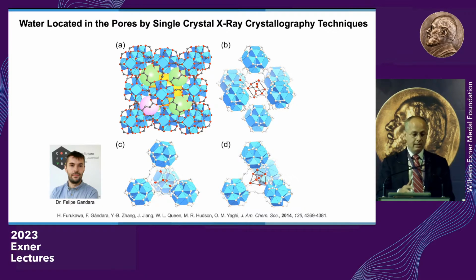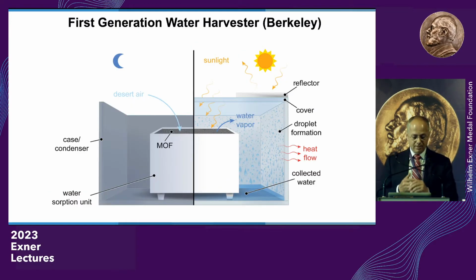And indeed, we never take these seeds out. They stay in the MOF. So when we take out the water, we only take out the water that comes after these seeds came into the pore. And so the student didn't believe that this could work.